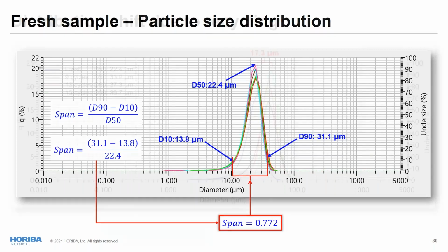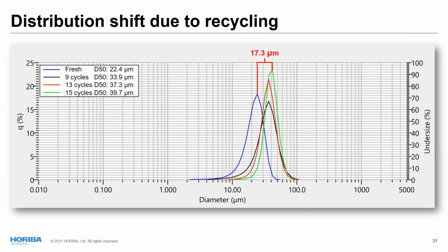So here, comparing the same samples that Matthieu showed the results for oxidation in other examples and in his analysis, we ran particle size on the fresh sample, the sample with 9 cycles, 13 cycles, and 15 cycles. And we see an increment of 17.3 microns from the fresh sample to the 15 cycles. And this is 77.2% change in your D50, which is a huge shift in particle size.